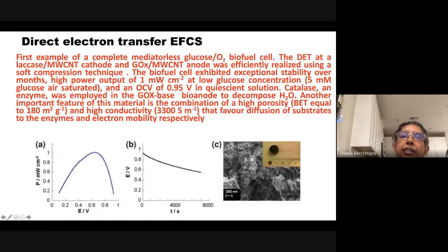The fuel cell that was developed was a mediatorless glucose oxygen fuel cell. The direct electron transfer was observed at the anode compartment, which is a glucose oxidase CNT anode, and also in the cathode compartment, a laccase CNT cathode. So in this fuel cell, a high power output of 1 milliwatt per centimeter square could be obtained at an OCV, open circuit voltage, of 0.95 volt. Another important feature is that this material was found to be highly porous and highly conductive, so it favors the diffusion of substrates to the enzymes, and the electron mobility was improved to a large extent.